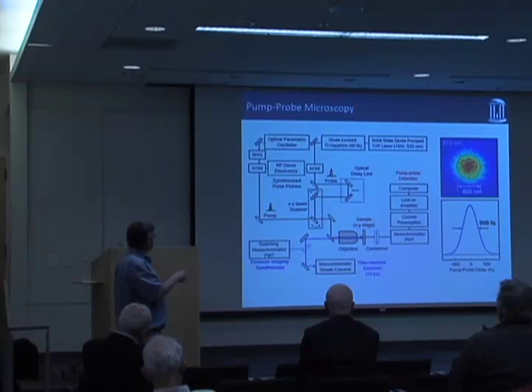The first part is basically a conventional pump probe spectrometer, right? We have a Ti-Sapphire oscillator. We have an OPO, so we can do 2 color experiments. We get 2 beams. One's called the pump beam. That's the thing that excites the sample. We have our probe beam. That comes along later at some well-defined time delay. Those 2 beams get recombined, and they travel into an objective, which focuses them down to a diffraction-limited spot. And they're overlapped with some structure in our sample.